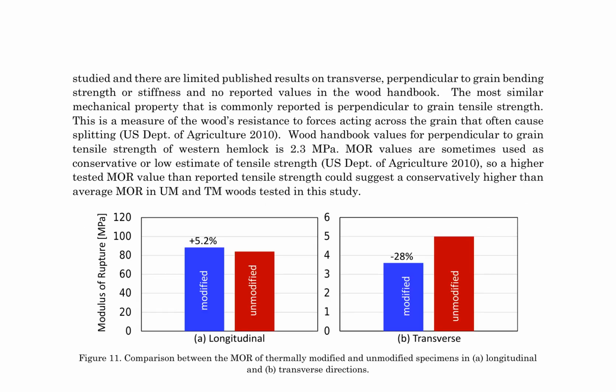This study delves into the mechanical properties of thermally modified and unmodified wood, focusing on the modulus of rupture, MOR, in both longitudinal and transverse directions. The results show that thermally modified wood exhibits a higher MOR in the longitudinal direction, with an increase of 5.2% compared to unmodified wood. However, in the transverse direction, the MOR of thermally modified wood decreases by 28% compared to unmodified wood, as visually represented in Figure 11.